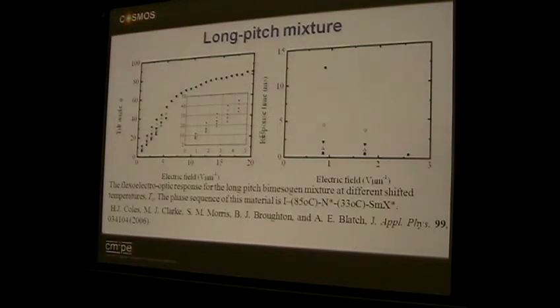If I flip through quickly, a long pitch mixture. Now, this may not surprise you, but it actually amazes me, the switching angle in this system, the tilt angle, is 83-84 degrees. Your helix is deforming from that helical shape and still staying more or less a helix, twisting right around, as the optic axis rotates through plus minus 83-84 degrees. So it's almost a right angle, and that's kind of difficult to imagine. But it is reversible and it does work.